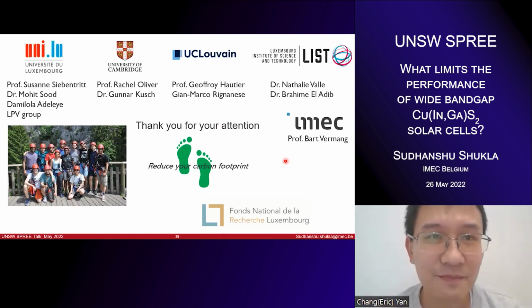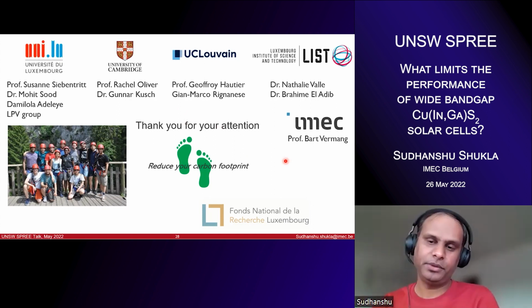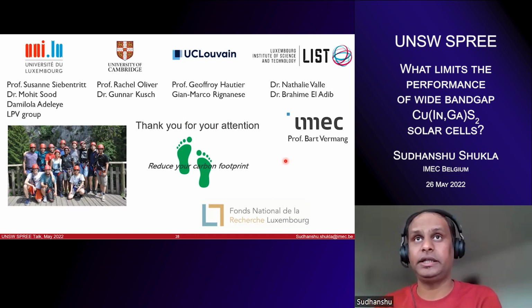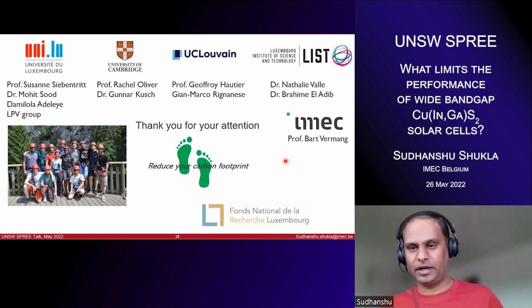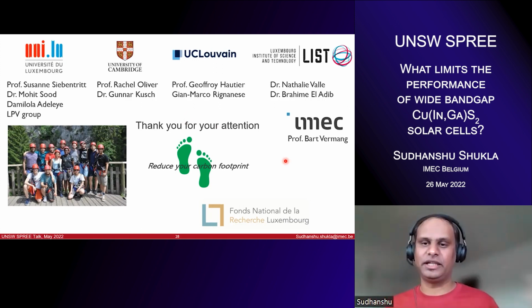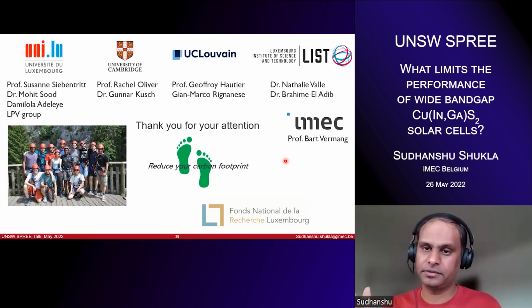Yeah, so what happens is that when you increase the band gap, because we are doing this co-evaporation process, having an identical film in all the runs is sometimes difficult because it's pretty much machine dependent. Sometimes you have all the sulfur that's condensed, so you have to clean from time to time. So conditions can change, but I think it is mostly related to the buffer. You have to optimize the buffer layer according to your absorber, and then you can improve the fill factors.